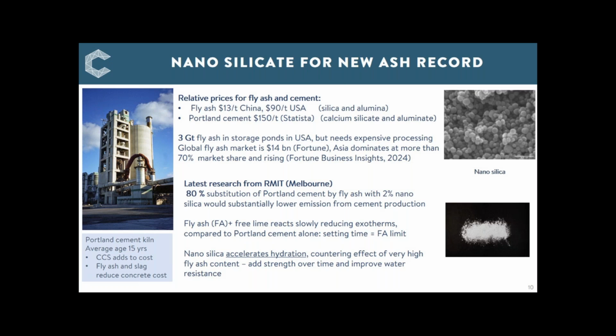How does it work? Well, it accelerates the hydration reaction. As you substitute more fly ash for cement, the setting time gets longer, and eventually that becomes impractical. But if you add nanosilica, that accelerates the hydration reaction, reduces the setting time, and so you can add more fly ash and achieve strength in a reasonable period. So that's a very exciting development in the cement industry to reduce energy use and emission.